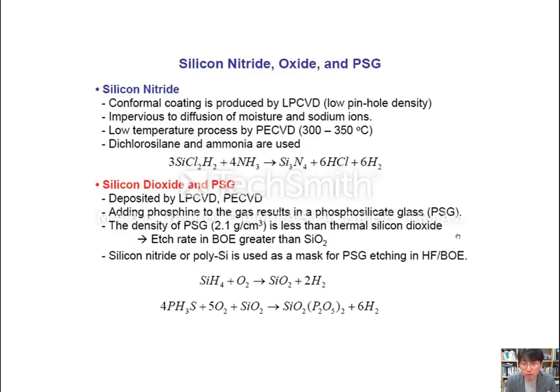Okay, so you need to test what their etch rate is compared to the other material, the etch rate using the BOE. So if you feel the density is not high enough to give good protection to those protected areas by the PSG, you should think about the thermally grown silicon dioxide. Otherwise, you're not going to get what you want. Okay. Also, silicon nitride or polysilicon can also be used as a mask for PSG. If you want to etch the PSG, then silicon nitride or polysilicon is good for the mask. Okay.